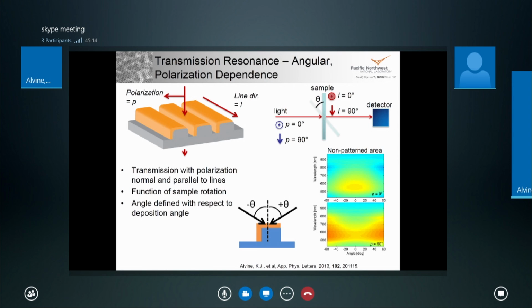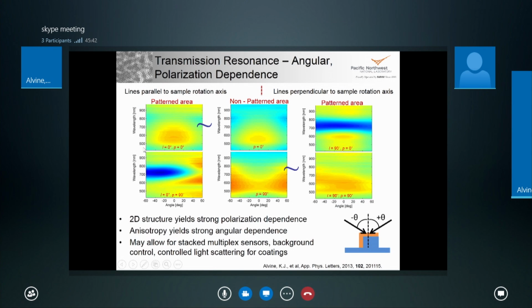The interesting thing about these, as I mentioned before, is that they are highly anisotropic. If you look at the polarization response in terms of this structure being rotated about the axis either parallel or perpendicular to the lines, with the polarization either perpendicular or parallel to the line grating, you can get very different responses. In both cases where you see the dark blue bands, those are the cases where the polarization is perpendicular to the lines, and there you're getting a strong nanoplasmonic response.